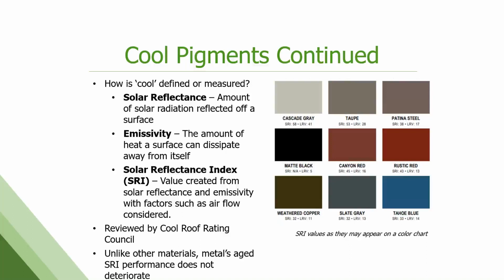The Cool Roof Rating Council is sort of the go-to third-party verifier for these properties, and not just for pre-painted metal, but any roofing or wall type of coating or substrate that needs to be listed gets checked by them. One really nice thing about pre-painted metal, because it is so incredibly durable and our colors don't fade or change over long periods of time, is that this initial SRI is going to hold for years and years, whereas other types of roofing products especially tend to degrade very quickly in the first few years, and the benefit that you're getting drops off right away. But with pre-painted metal, it really doesn't. So the 3-year aged value is what most agencies list.